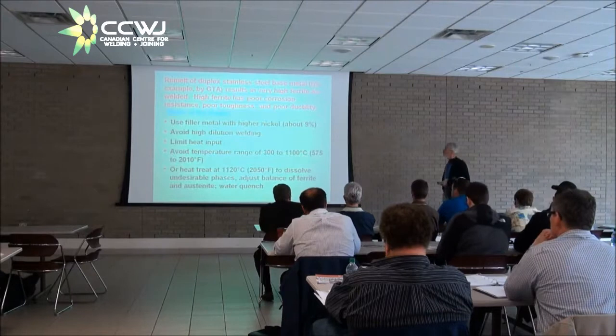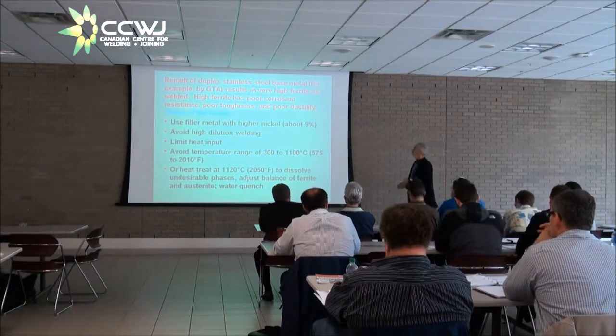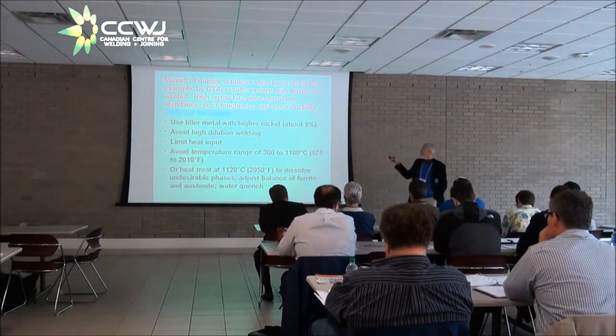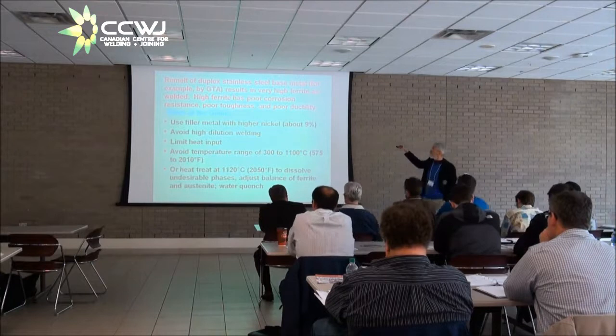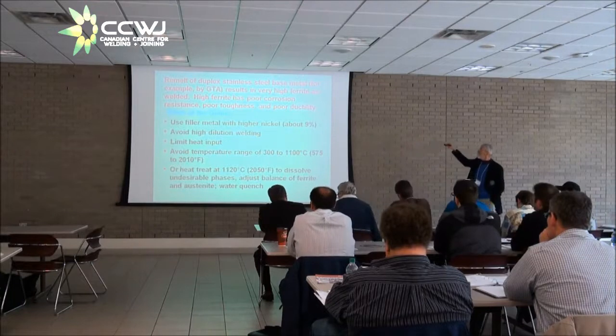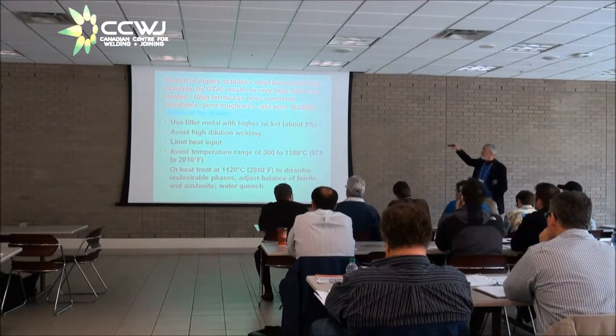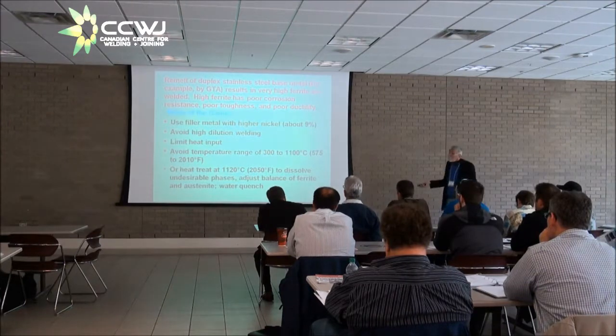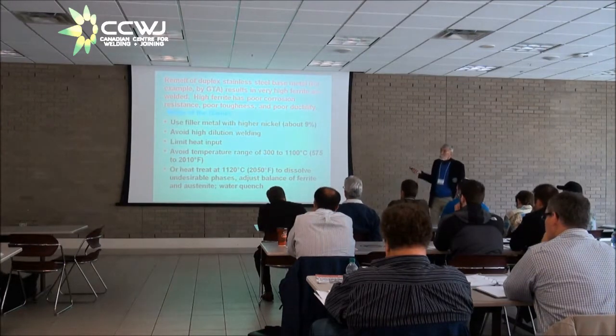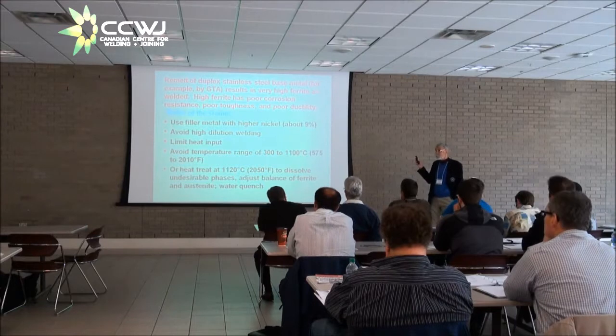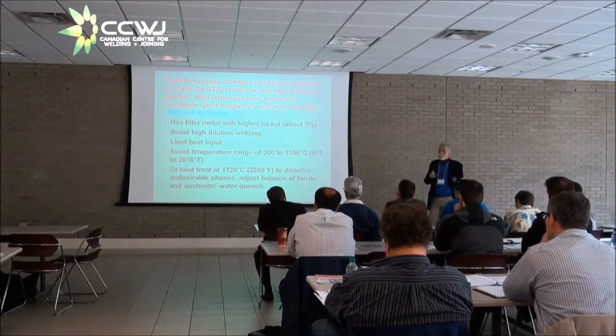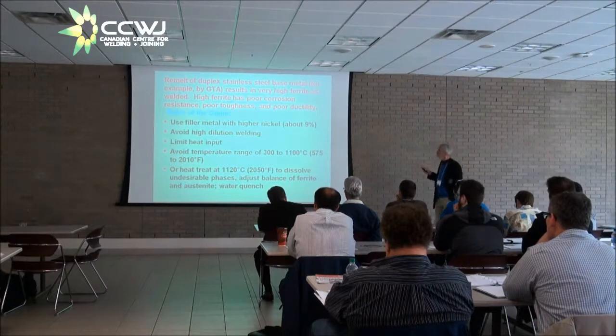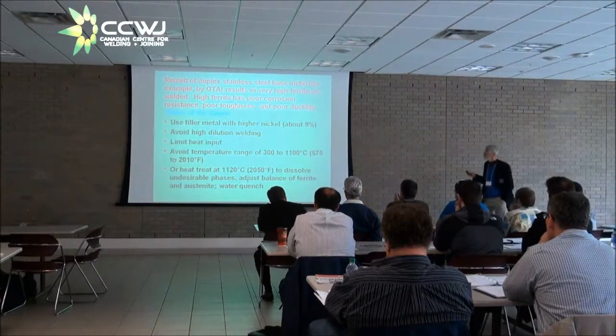Okay, so we get to the, I just want to re-emphasize one more thing, and that is if you remelt duplex stainless steel by gas tungsten arc welding, you're going to get high ferrite. If you try to dress the surface with gas tungsten arc without filler metal, you're asking for trouble. You don't want to do that. I think Ellen said that this morning, and I completely agree with her there.